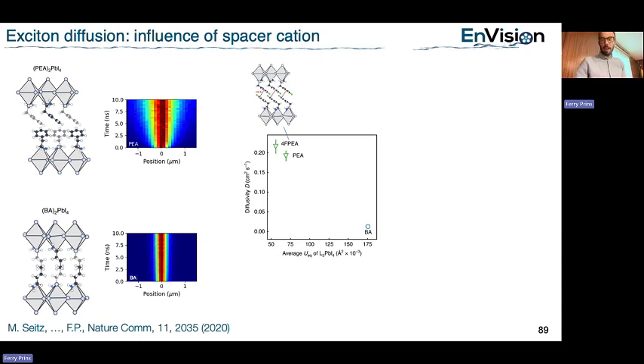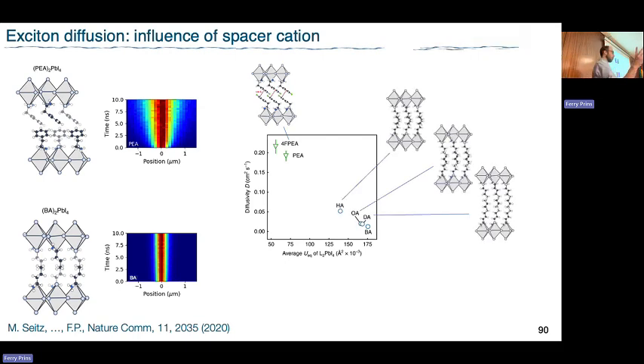You can also change the length of your alkyl chain when you make your butylammonium, and make the whole family. Where now you space it farther and farther apart, everything becomes even more floppy. You can see a very clear trend of higher diffusivity with higher rigidity. This is now what we would call a structure property relationship, where you can say the design parameter apparently is rigidity.